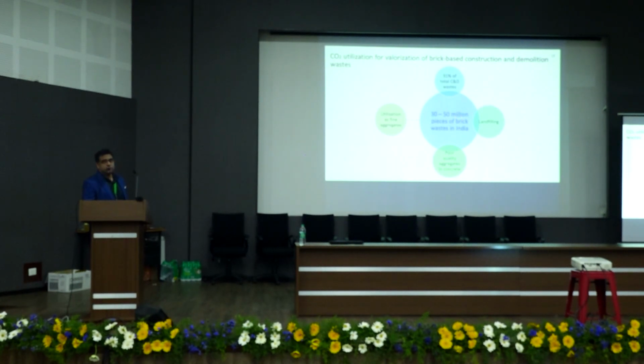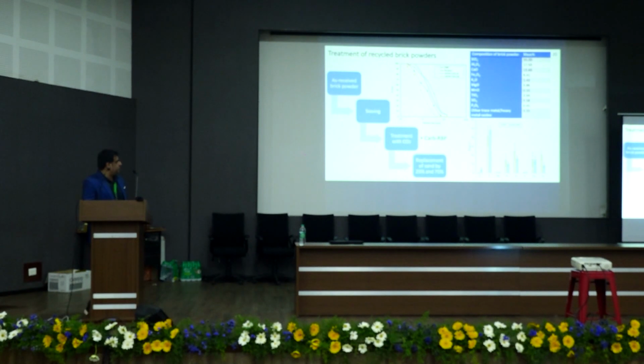Brick waste as such can be used as fine aggregate or even coarse aggregate, but what happens is that the interfacial zone that is created around this brick powder is very poor compared to the bulk matrix, so that is detrimental to the engineering properties, right? So now can we use CO2 to make it better and then utilize it as fine aggregates? So with that in mind, we developed a process. There are certain process conditions. So we have the brick powder, we sieve it. We have the sieve size analysis, which closely conforms to the M sand that we get in Bangalore. And then we treat it with CO2 under a certain process condition and flow rate, right? And then we replace sand, M sand, at 25% and 75% by mass.